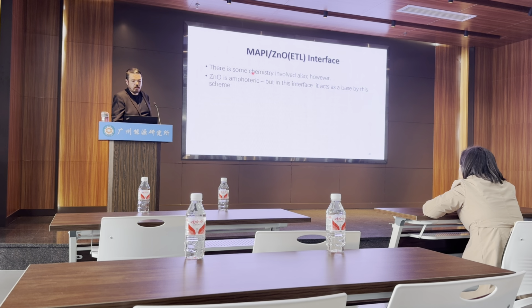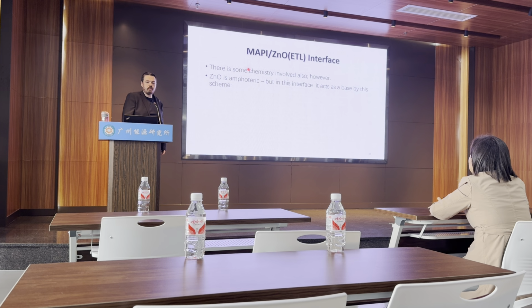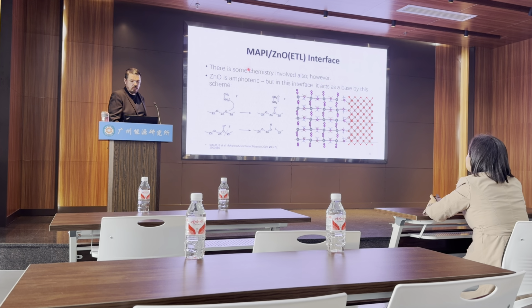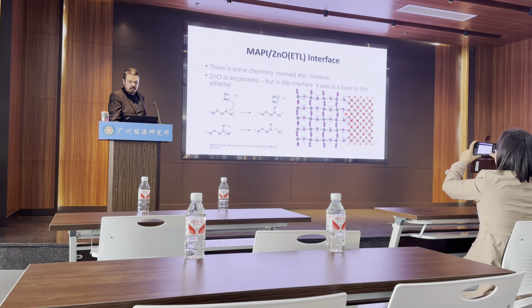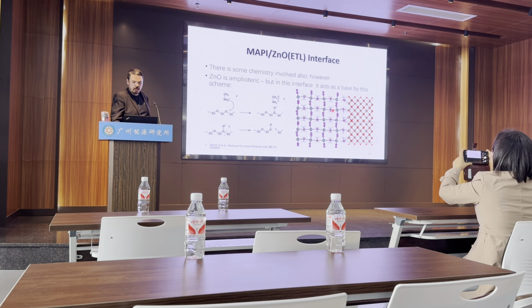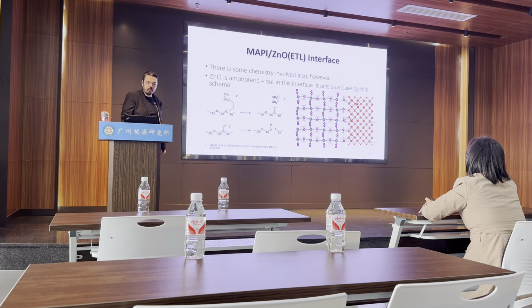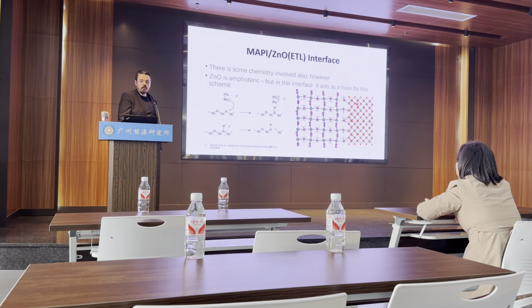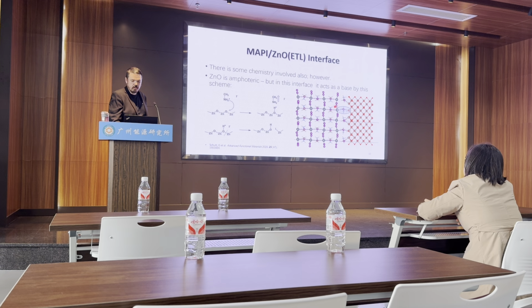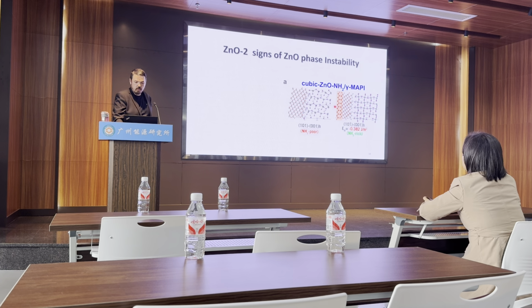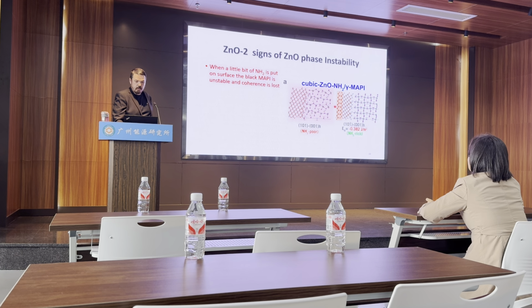The chemical problem is that the zinc oxide surface is amphoteric. When you mix it with perovskite, it's basic. And DFT tells the story perfectly. Our MAPI, methyl ammonium itself, gives away its hydrogen to the zinc oxide, and you can see it right there. That's the problem, and it always happens if you launch this calculation this way. It's reproducible.